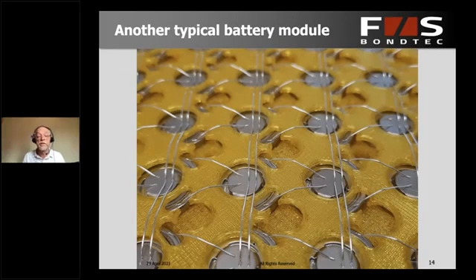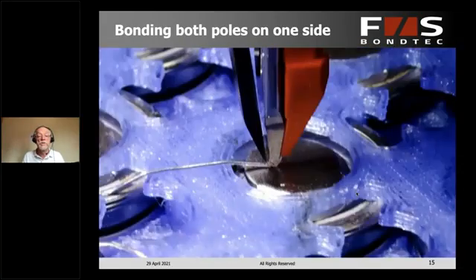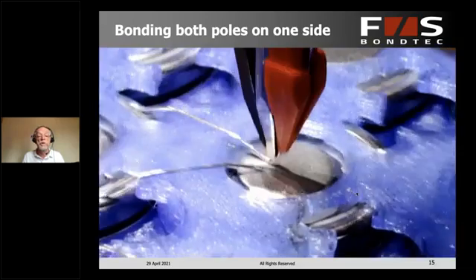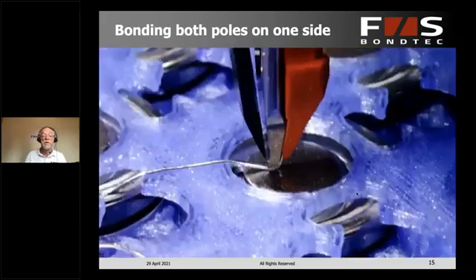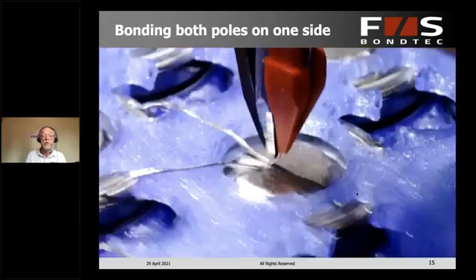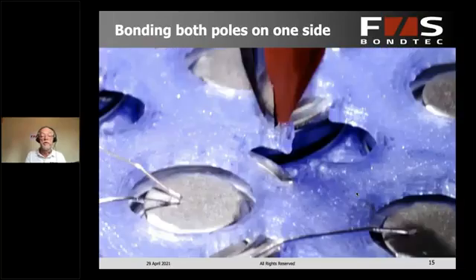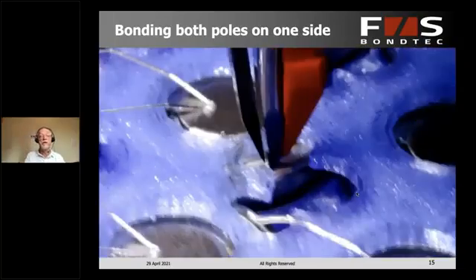In a case like this, where you can see another module that we've shown here, we have the two connections from the plus pole and an extra connection from the rim to a plus pole, as you can see here. So here you see the bond running from the rim to the neighboring plus pole. And of course, here we have a much smaller area where the bond has to go on the rim, and the rim is in addition bent and curved.